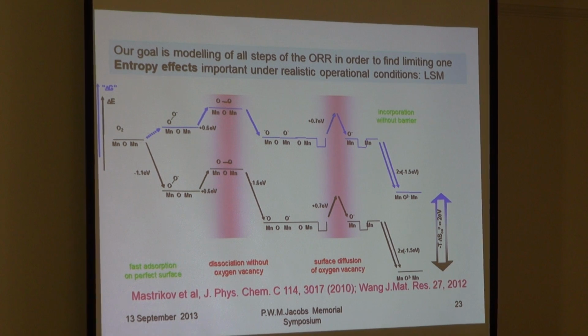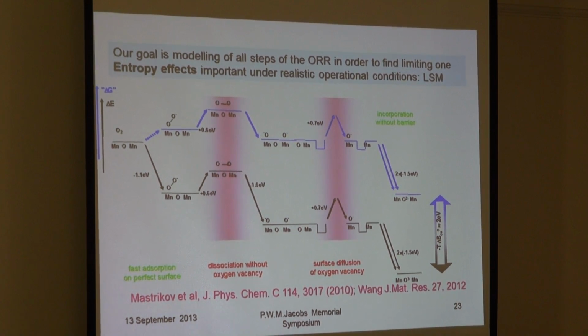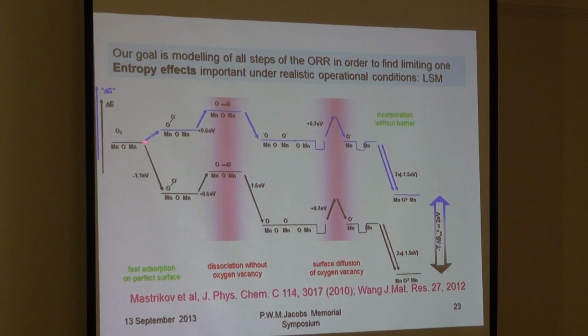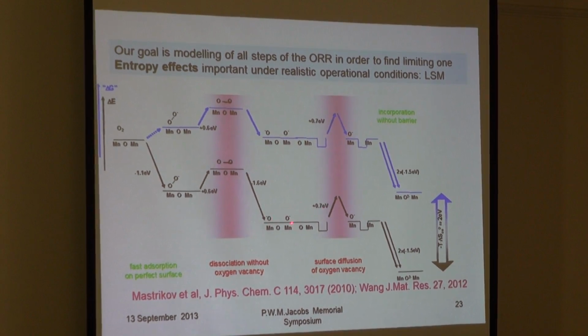Okay, so step by step we calculate the energetics of all elementary processes in oxygen reduction in order to calculate the reaction rate and to find out the rate determining steps. And this is an illustration of what we did for lanthanum manganate, and now I performed for BSCF. So essentially this illustrates that oxygen is adsorbed on the manganese terminated surface like a tilted molecule. Next it could dissociate, which takes quite low energy, about 0.6, 0.8 electron volt, which is energetically very favorable. So as a result of dissociation of the oxygen molecule at the surface, we have O2- ions sitting above manganese.